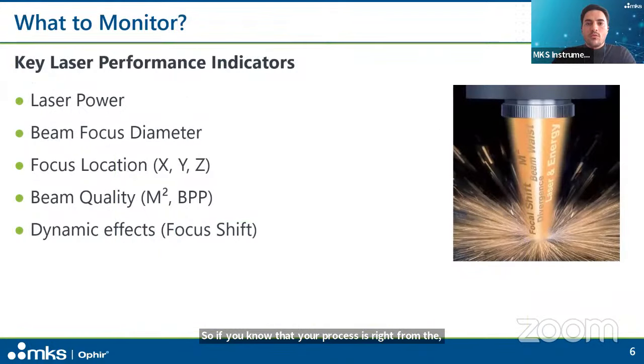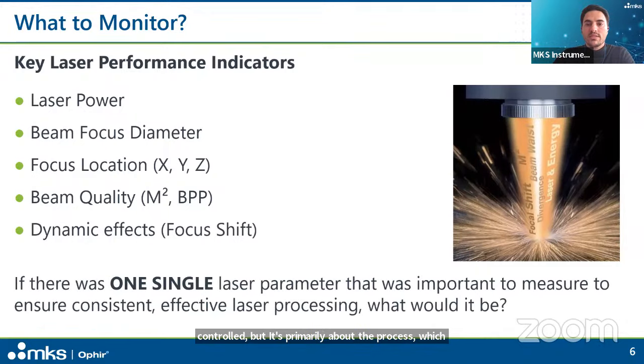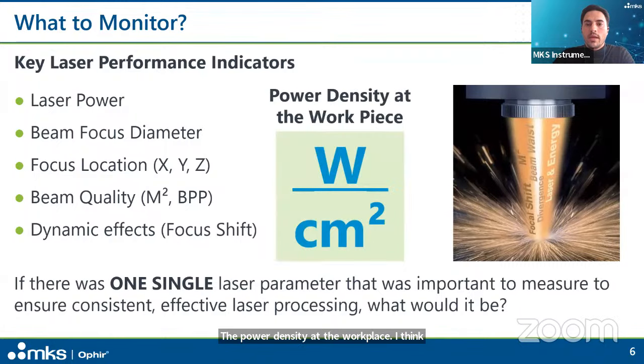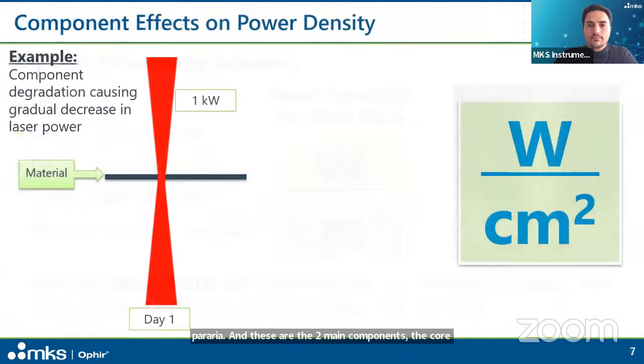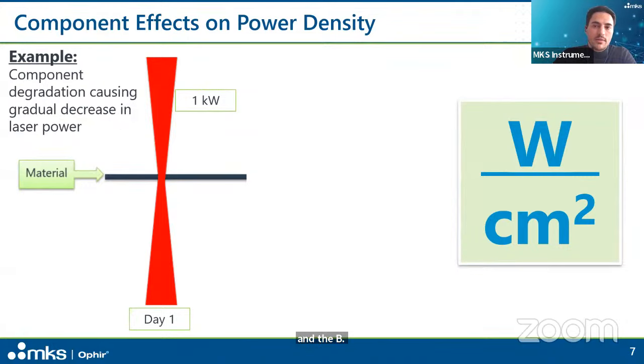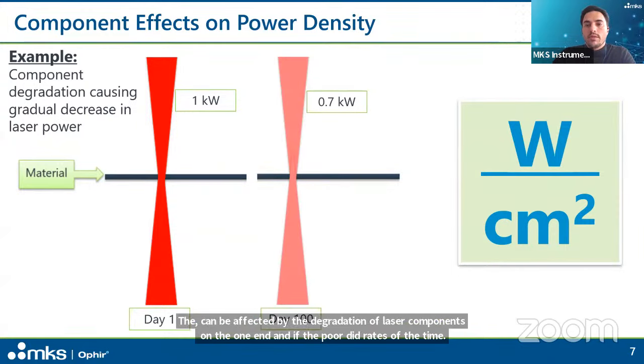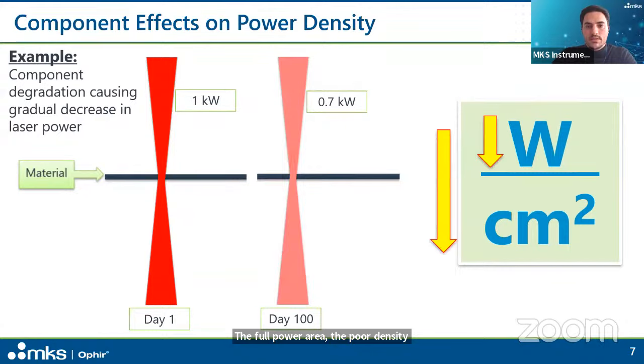So there are a whole variety of laser parameters that can be controlled, but it's primarily about the process. Which process parameter is the most important? The power density at the workpiece, but it's the power per area. And these are the two main components, the power and the beam area, that we address with the measurement technology. The power density can be affected by the degradation of laser components on the one hand, and if the power degrades over time, the power per area, the power density also automatically decreases.